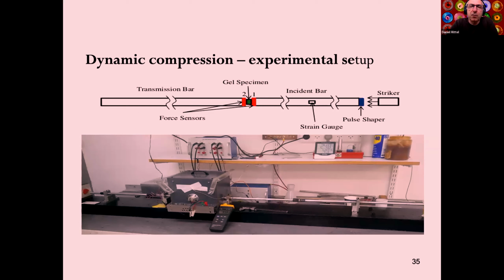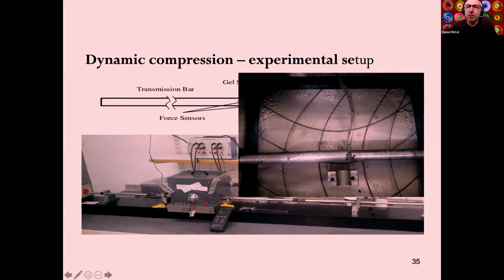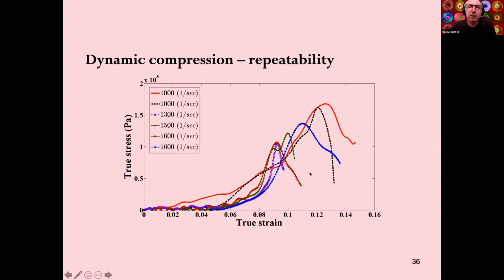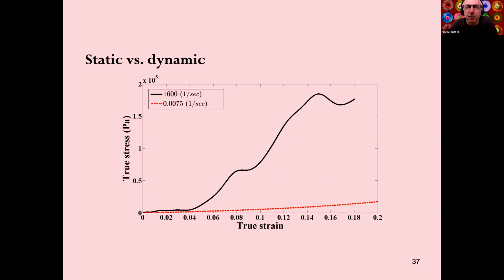We started with that with ballistic gelatin several years ago, and now we're onto those gels. And the thing that you see here is basically a furnace with water, because you need to hydrate your material. If you heat it without hydration, then it will simply desiccate. So this is a close-up. Those are the heating wires, but the specimen is here, in fact, and those are the FlexiForce wires, leads, sorry. Dynamic compression, again, repeatability at various strain rates. Generally speaking, the curves are nicely repeatable given experimental uncertainty. Well, static versus dynamic, there's, as expected, a very strong difference.